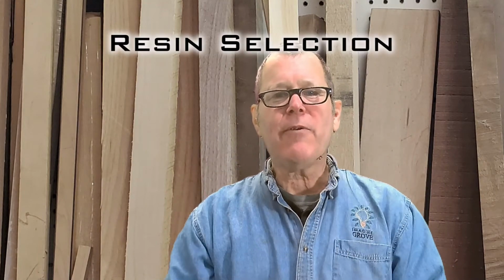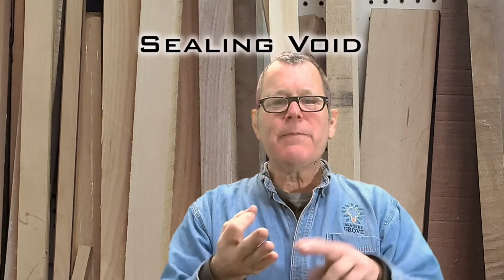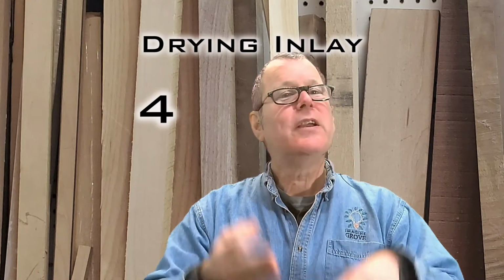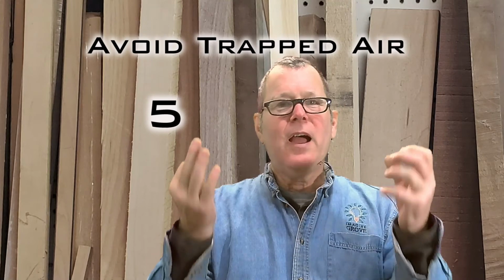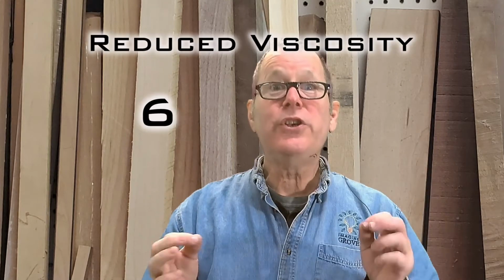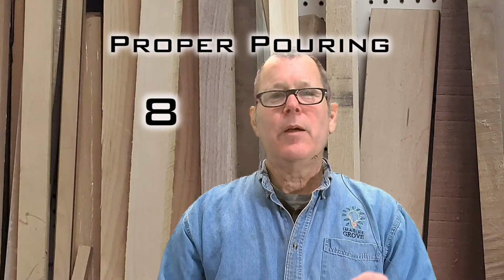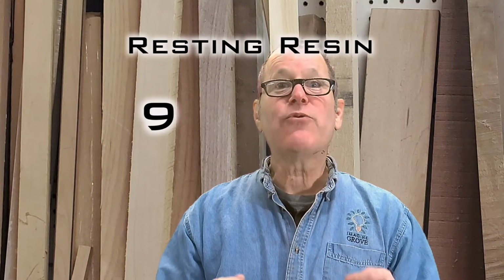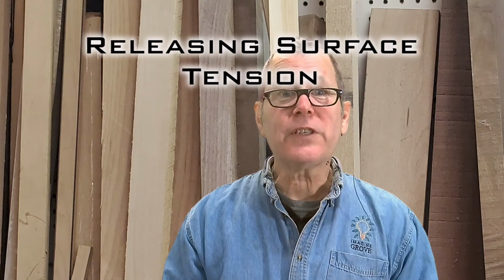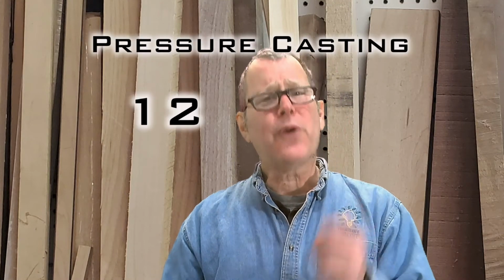We have picking the right resin, sealing the void, sealing the inlay, drying the inlay, avoiding trapped air, reducing the viscosity, degassing, properly pouring, letting the resin rest, releasing the surface tension, overfilling, or pressure casting. So there's 12 tips to give you a better casting.